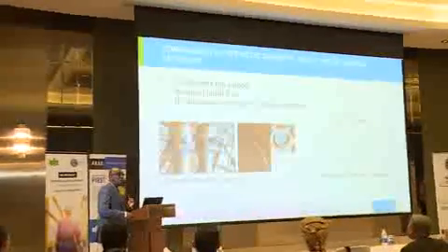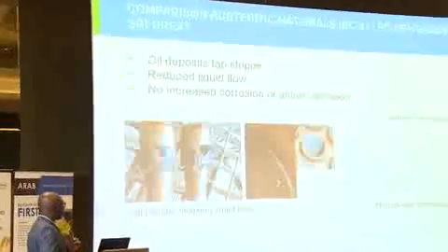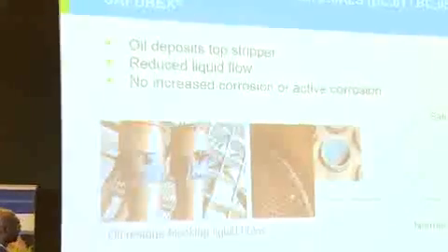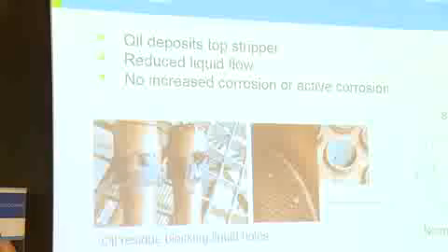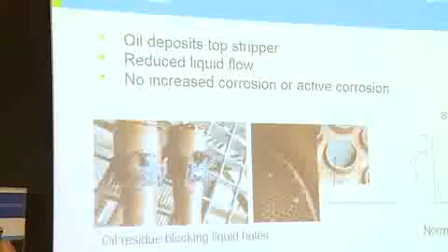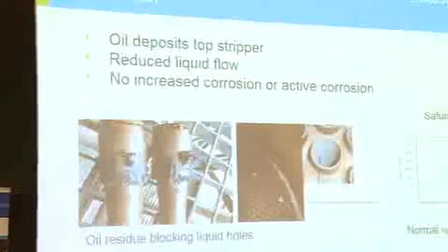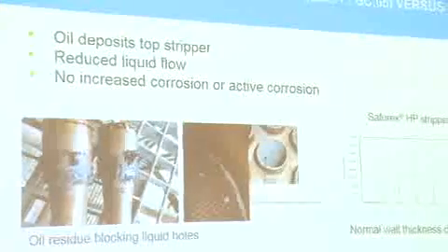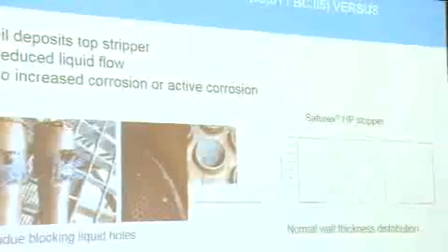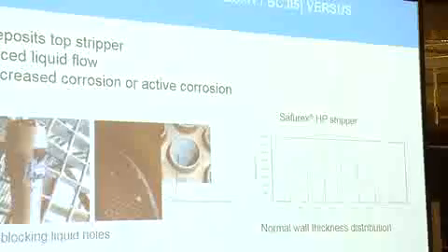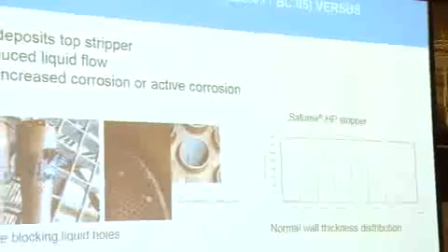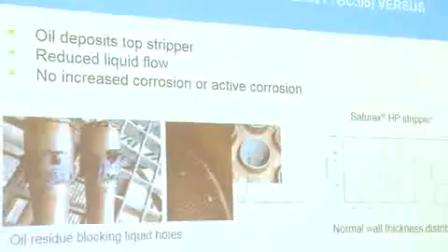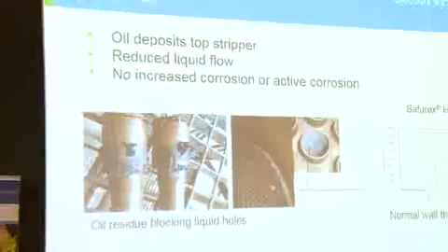But in this case, the plant ran. When the plant was shut down for the turnaround, our inspectors went there and carried out inspections, and the good thing was that when we looked at the distribution of the wall thickness, it was normal, as we expect. Because in other situations, you would find out that the tubes which are running dry would have a higher corrosion rate and less wall thickness compared to the tubes which have some liquid in them. And also, the tubes which were thinner were not related to those which were running dry. You could not make that distinction.